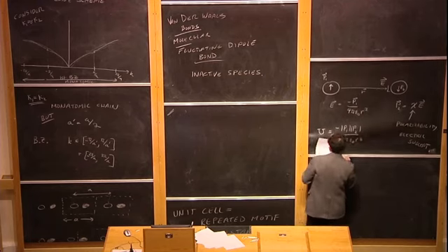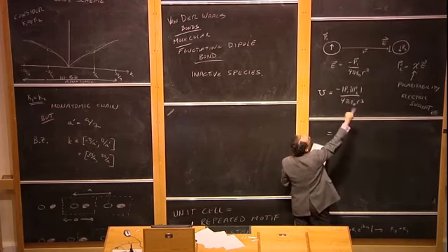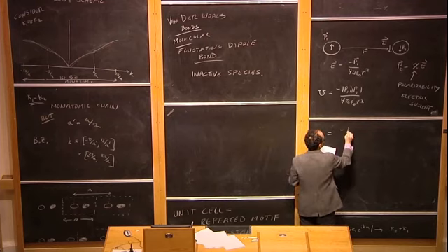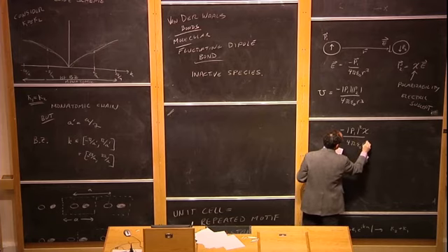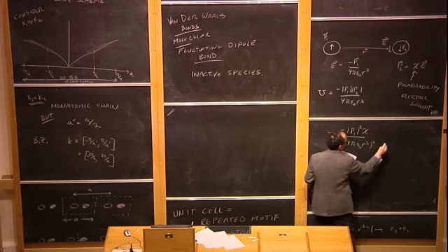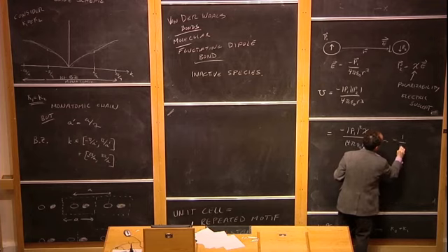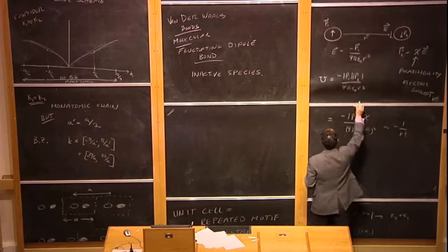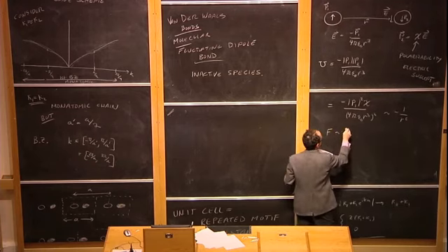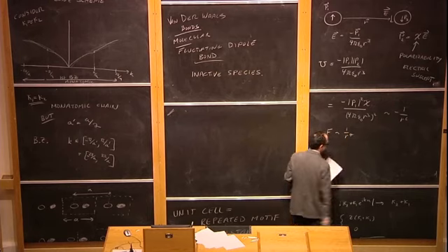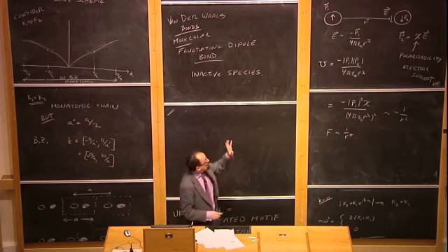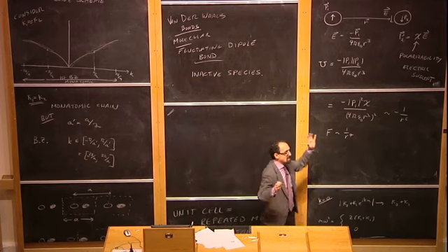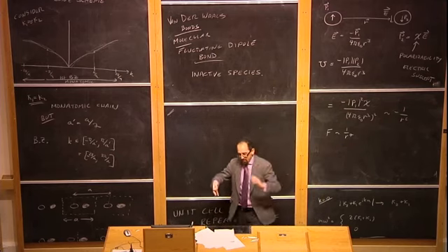cubed. So the total energy, just plugging these things all together, we get minus P1 squared chi over 4 pi epsilon naught r cubed, all squared. And in particular, this is negative and goes as 1 over r to the 6th. So the force goes as 1 over r to the 7th. Now, that's more or less how the calculation goes: you have a polarization in one atom, it induces a polarization in the other atom, and the polarizations attract.